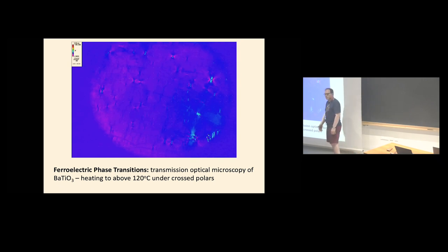Okay, so we have gone through a phase transition on heating where it was anisotropic, the indicatrix of the material was anisotropic, and now it's become isotropic. And that is coincident with the phase transition between it being ferroelectric and being non-ferroelectric or paraelectric. Okay, so in all of this discussion, it's really the paraelectric to ferroelectric transition that we're going to focus on.